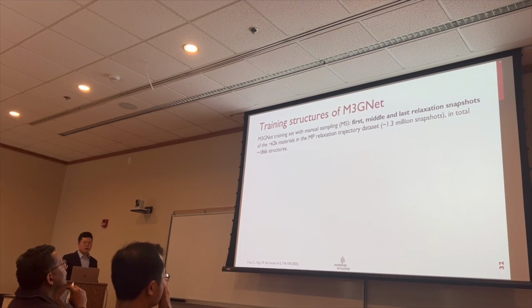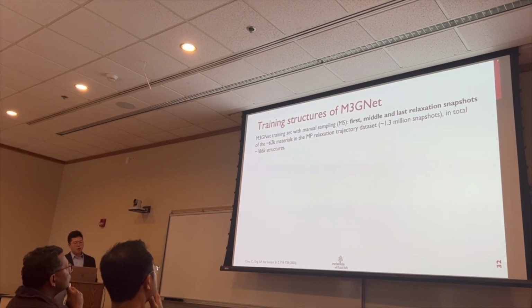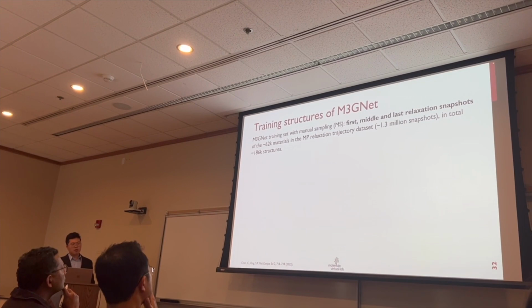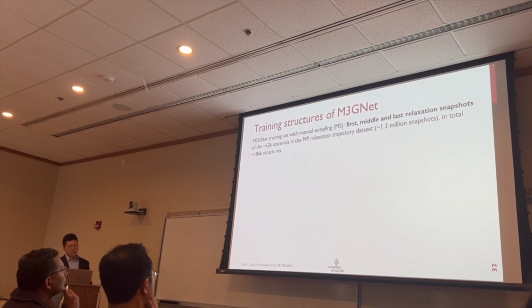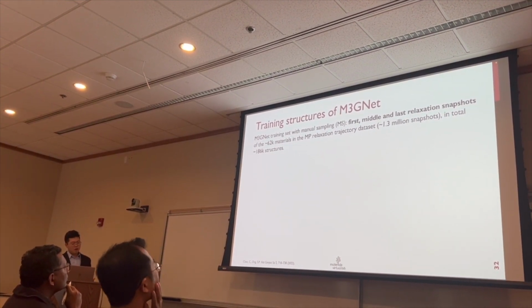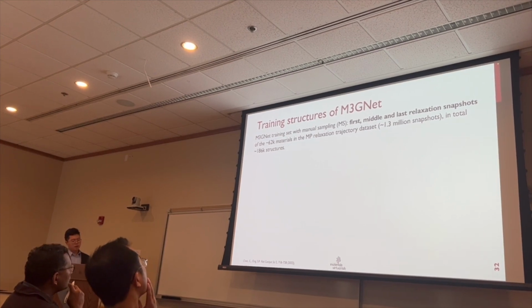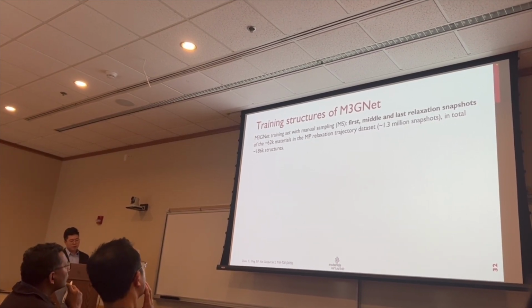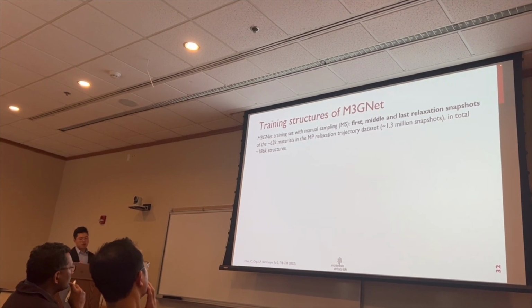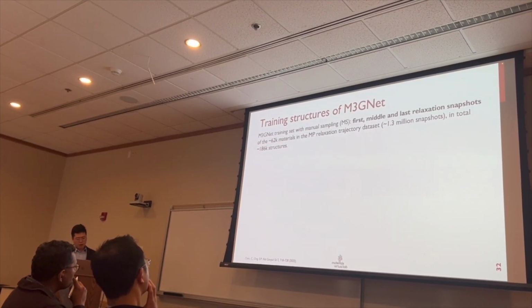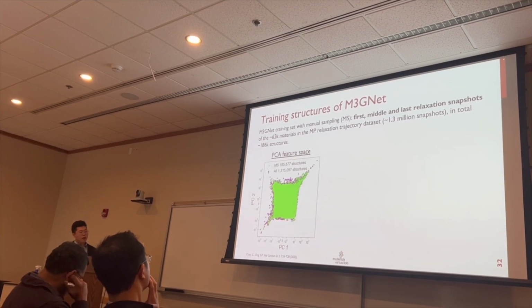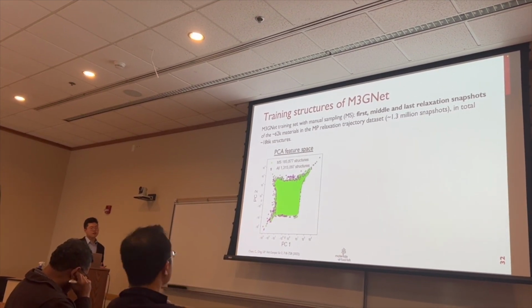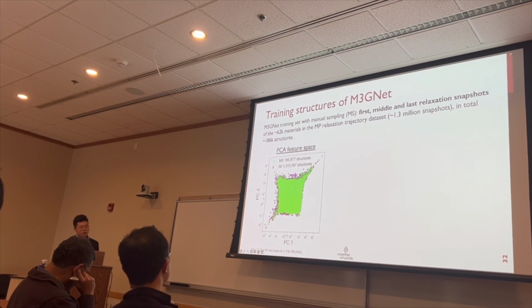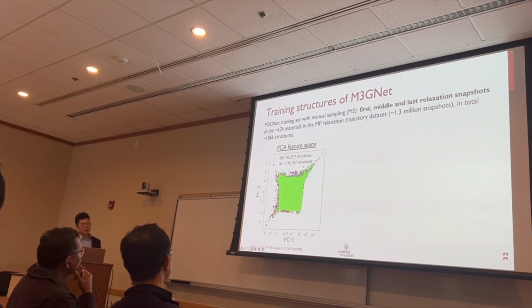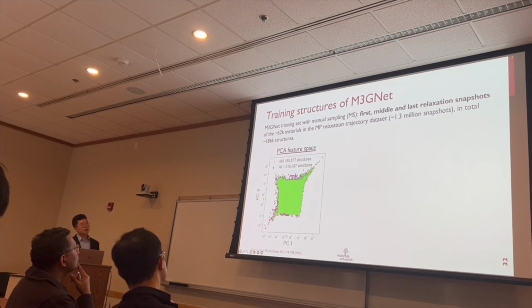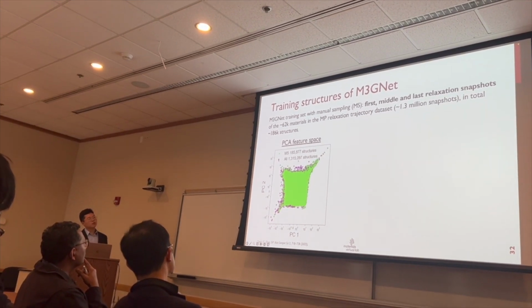Let's first look at the existing training set of M3GNet, which is built by a manual sampling method, which selects the first, middle, and last relaxation snapshots from the 62,000 materials in the Materials Project relaxation trajectory. And this attempt was to sample a diverse structure space. But if we look at the PCA space of M3GNet feature, we can see that although these green dots cover the majority of the feature space, there are definitely some regions on the boundary of the feature space that are